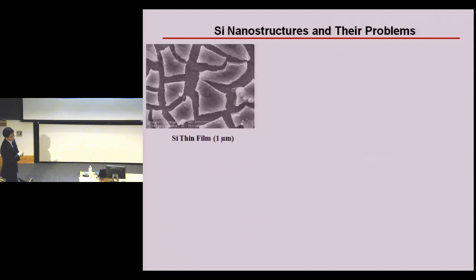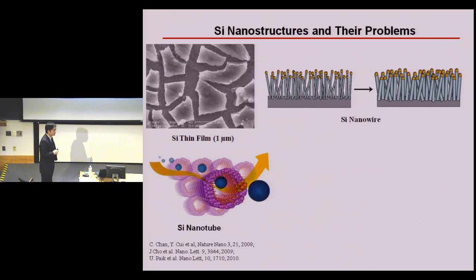So this is what happened for a silicon-based lithium-ion battery. It was a thin film. After a few cycles, you can see here, the silicon thin film breaks into pieces. So this is not acceptable for battery application. That's the reason why in the past 2 or 3 years, silicon nanostructures have attracted a lot of attention. And this is a structure for a silicon nanowire-based battery, and this is for a silicon nanotube-based battery.